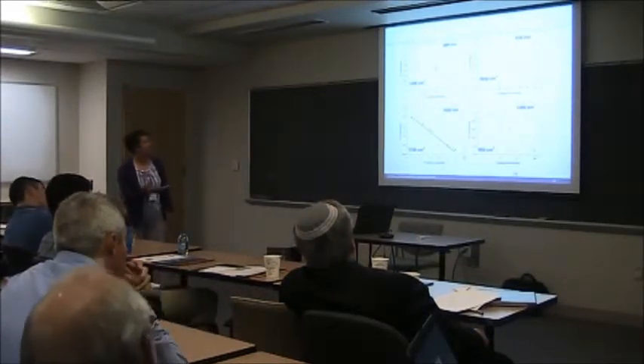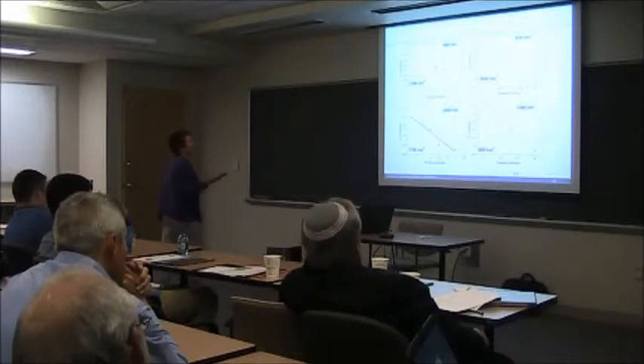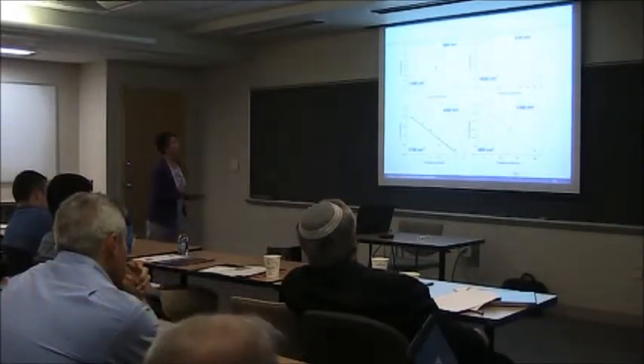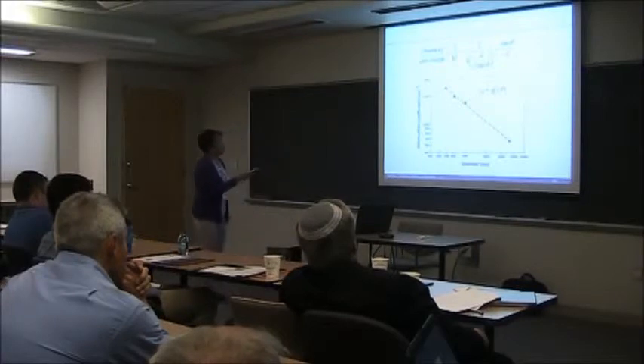We did that. We decided to look at some different diameters and got an interesting result: the coefficient that we measured, the absorption coefficient, alpha, actually varied with the diameter of the wire. Okay? And when we plotted that, we saw, so I'm calling it the attenuation coefficient, because it's not just absorption in the traditional sense.